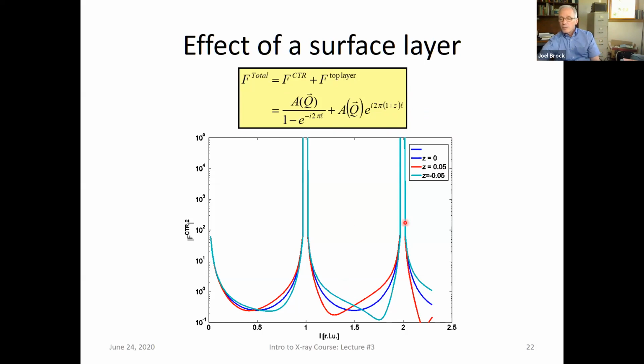You can see if I expand it by 5%, that's the red curve. Well, first blue is the original one coming through here. But if I expand it 5% in this region, it's suppressed. Remember, this is a log scale, so this is a big effect down in here. And on this side of the peak, it's enhanced. If I go out to the even order peak, it's reversed: here it was suppressed and here it was enhanced. You can see that, very characteristic.